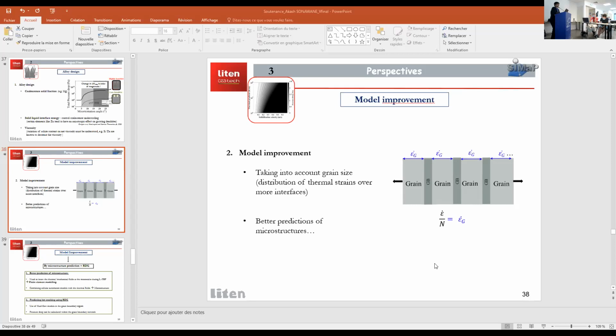You see, by the way, I come back to this, and I'm going to finish on this. Crack propagation and crack initiation. Imagine you have a crack, you replace a grain boundary by a crack. Epsilon dot goes back to 0 on that liquid film. So you see, it's not for you especially, it's for many people working on hot cracking. Propagation is not initiation. True, true. Completely agree, yeah. Propagation is not initiation.